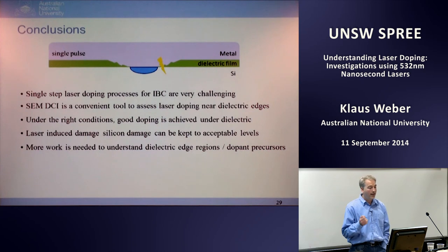We know that we can get good doping underneath the dielectric if we choose our conditions right, but it's not a huge parameter window that you have. And we know that we can keep this laser-induced damage to acceptable levels, even when we have multiple pulses in the same spot. But we need to do a lot more work to understand what's really happening in these dielectric edge regions, so we've barely scratched the surface in terms of that.